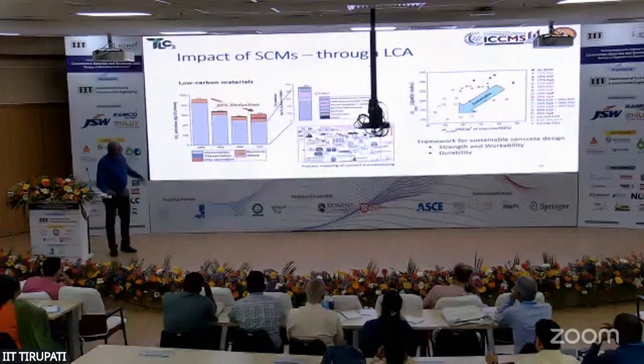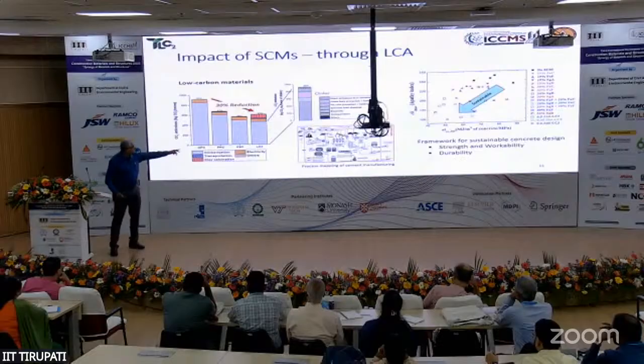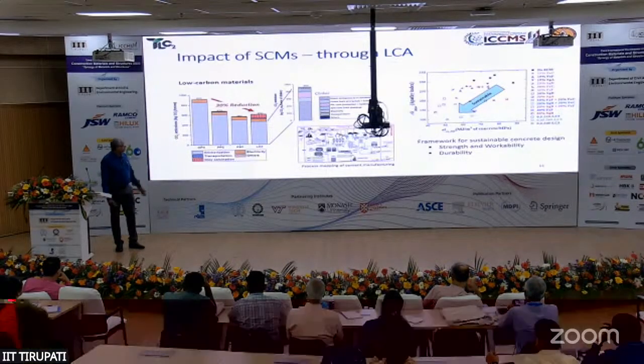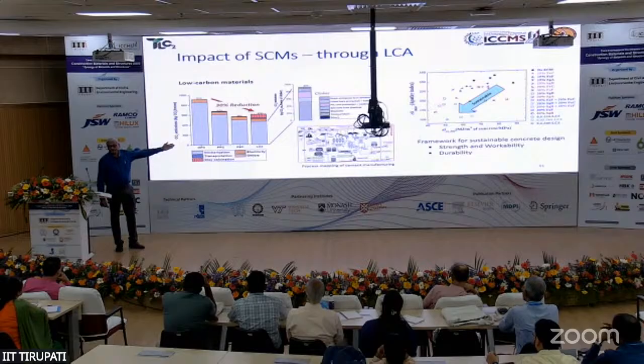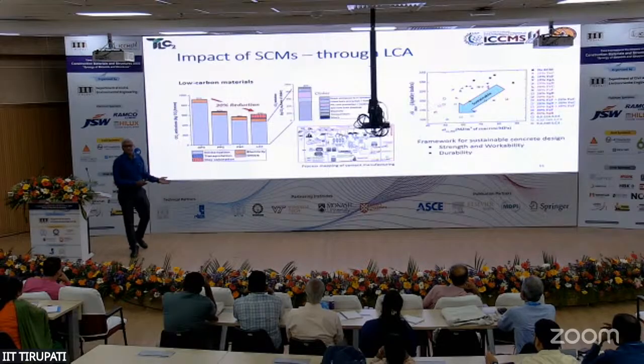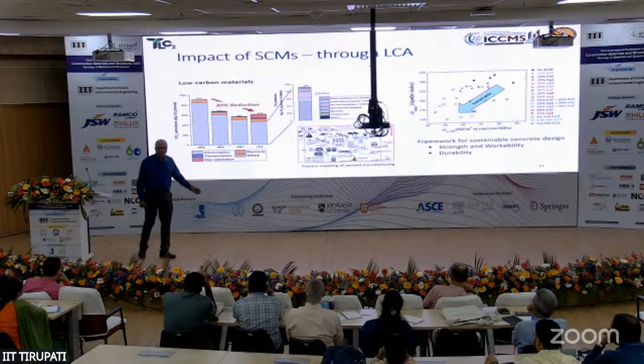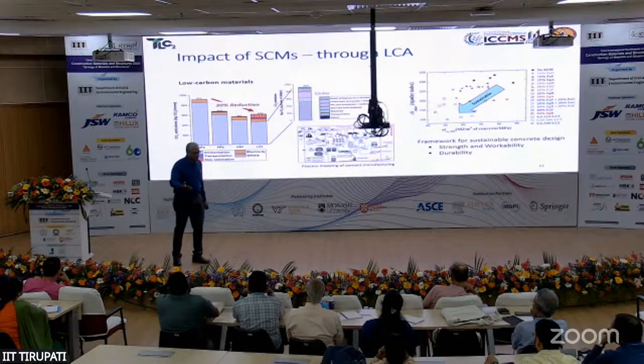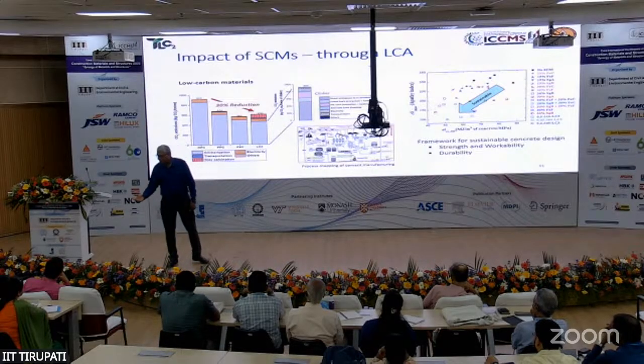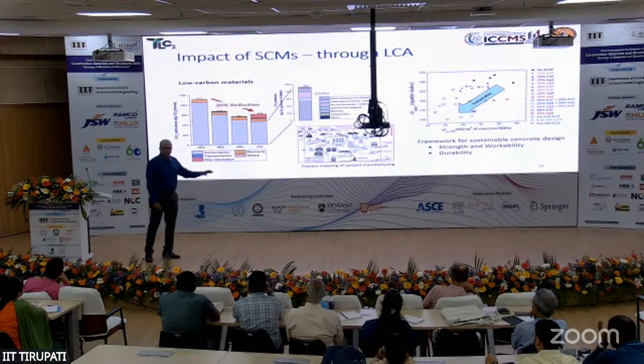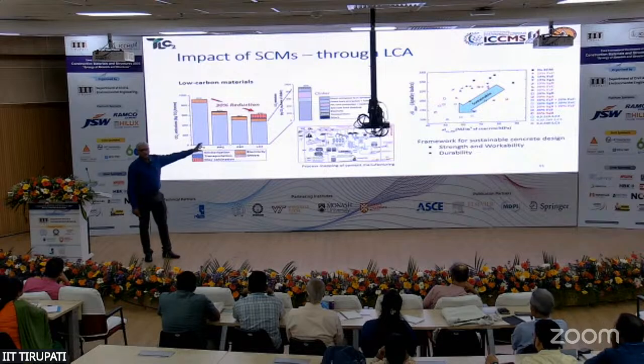And with that, we were able to calculate that your blended cements had much lower CO2 emissions overall, like your Portland slag cement, obviously because we are using very high quantity of slag as a cement replacement, is leading to a much lower emission as compared to OPC. Now, it's not enough to just say that you're emitting less. Are you emitting less over a life cycle? Are you also producing durability in the concrete? So that's where we actually combined the emission aspect with the actual durability in different types of exposure environments.